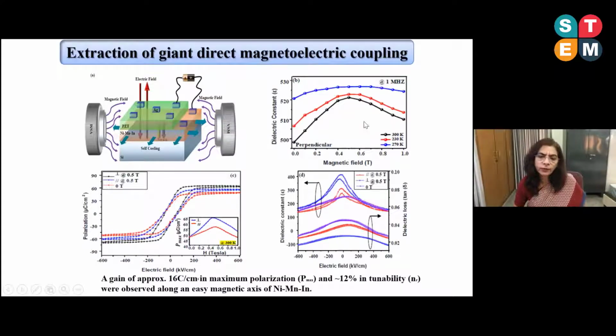We also carried out measurements of P loop at magnetic fields of 0 Tesla and 0.5 Tesla, both parallel and perpendicular to the axis, and the dielectric constant versus magnetic field and versus electric field. A gain of approximately 16 microcoulomb per centimeter square in maximum polarization and 12% in tunability were observed along the easy magnetic axis of the FSMA material.